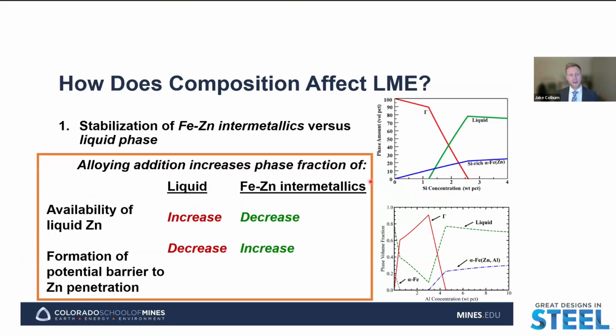Whereas instead, if that alloying addition is going to increase the phase fraction of iron-zinc intermetallics, and again, most notably the gamma phase, then we would have a potential decrease in the availability of liquid zinc, as well as a potential increase in forming that barrier to zinc penetration. So we see, again, increasing liquid fractions being detrimental for LME susceptibility, and increasing the iron-zinc intermetallic phase fractions being positive for LME susceptibility.